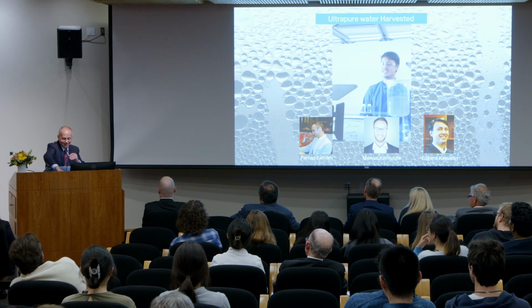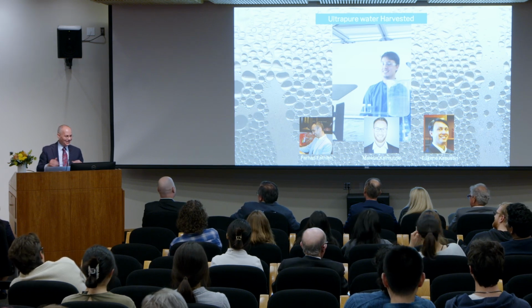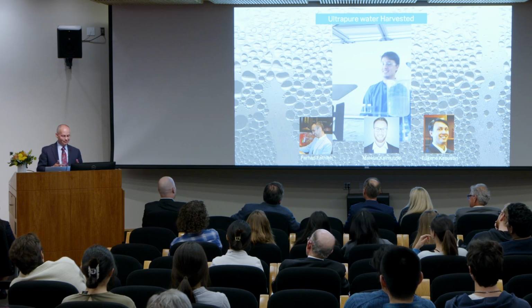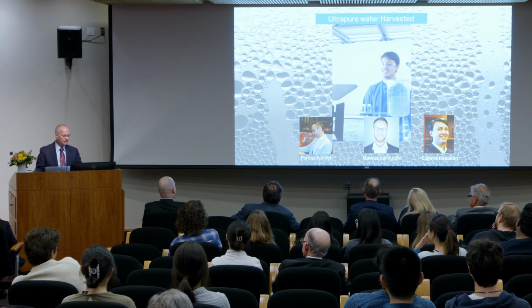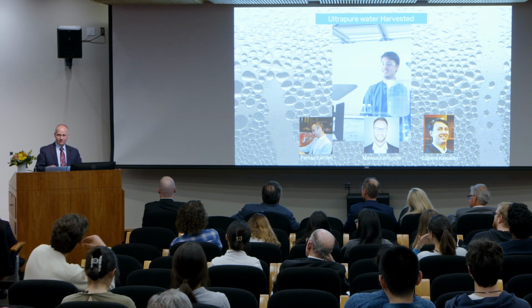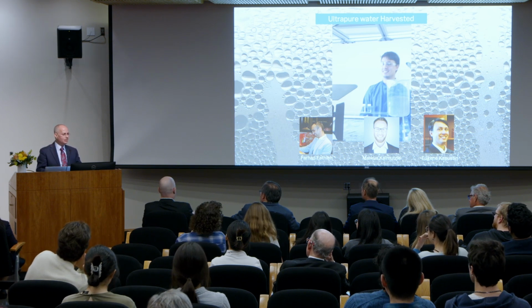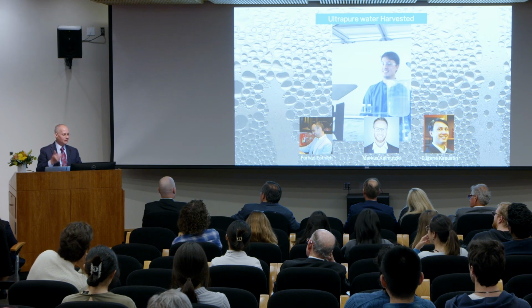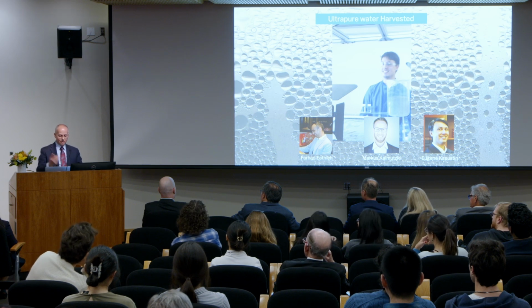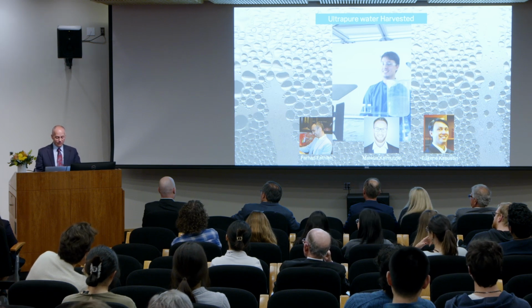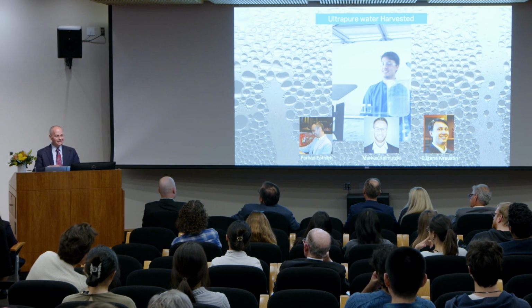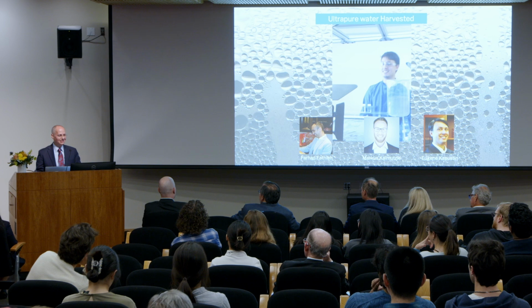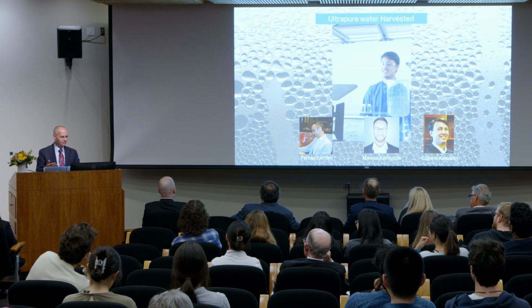Okay. By the way, he is alive and well and running a startup. But we have reported in this paper a scientific study that tested the water, metal content, organic. It's the cleanest water you will ever have because the MOF is a filter, only allows water in. The pores are large enough for water to come in, and it goes through phase change. And it's very, very pure water. It doesn't taste as good as Eugene advertises because it's distilled water. So if you mineralize it, as we would mineralize our drinking water, it will taste very good.